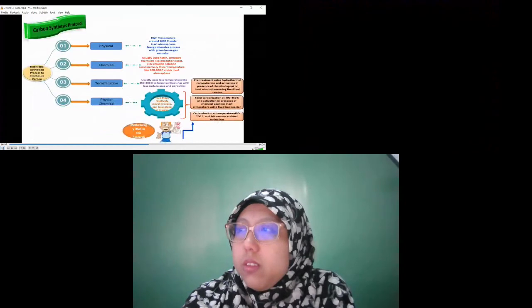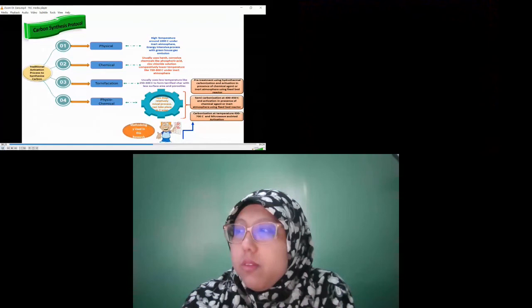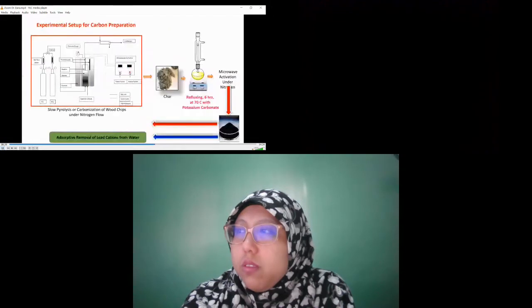Let us see why we are interested in the physicochemical method. It is a two-step method. It will give clean carbon because there will be less tar formation. In the secondary step, for activation, we will use microwave-assisted pyrolysis because it ensures volumetric heating, and the sample will be heated up in a very small amount of time. This is our fixed bed apparatus.